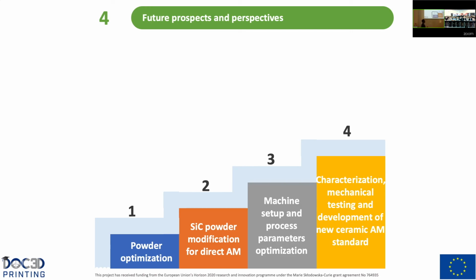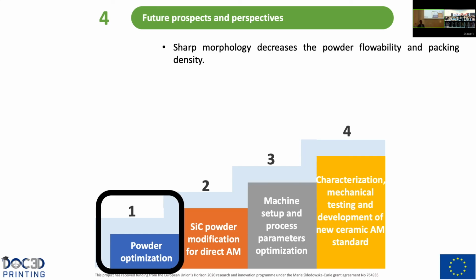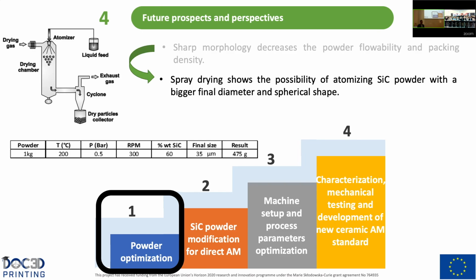So regarding the future prospects and perspectives of this project, first, the powder optimization. Actually, we were using a sharp morphology in the initial powder mixture that decreased the powder flowability on the packing bed. So in this regard, for example, spray drying shows the possibility of atomizing silicon carbide powder with a bigger final diameter and spherical shape. Actually, we are performing some preliminary experiments, and now we are able to obtain silicon carbide powder with a final size of 35 micrometers, and of course, the spherical morphology.